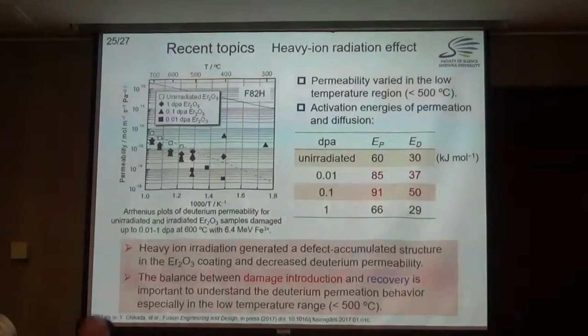Then in the case of ion irradiation, we evaluated the Er2O3 coating with ions. Fe 3+ 6.4 MeV ions were used, evaluated up to 1 displacement per atom. The result was good. After irradiation, the permeability decreased, not destroyed, so some crystallization or something like that is improved by irradiation. Of course, we have to increase the dpa, displacement per atom. The damage concentration in a fusion reactor is up to 100 dpa, but so far we have reached 1 dpa. The situation is very good.